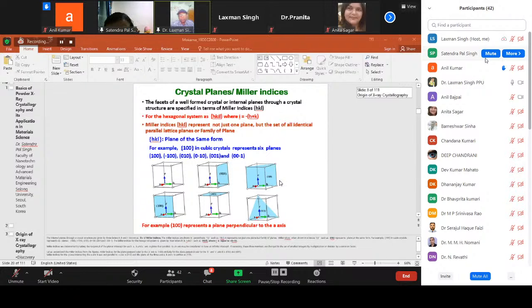The distance between 010 planes will be equal to the b-axis in the cubic system. So if you index, the lattice parameters a, b and c should be equal to the d spacing, like 100 or 010 or 001. So lattice parameter and d spacing will be equal. That we saw in that case.